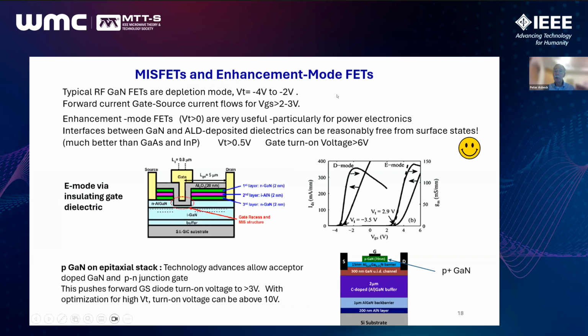Another issue associated with processing of nitride FETs, a very fortunate one, is that the nitrides are a bit more tolerant, resistant to formation of interface states in ALD deposited dielectrics, and the nitride allows different dielectrics to be deposited in order to form a MOS or MIS structure. This is favorable for making enhancement mode FETs, such that when you forward bias the gate source junction, you don't get current flow at 1 or 2 volts, as in conventional devices.